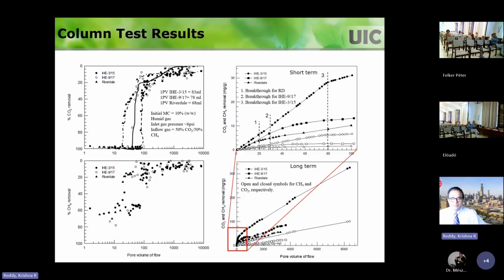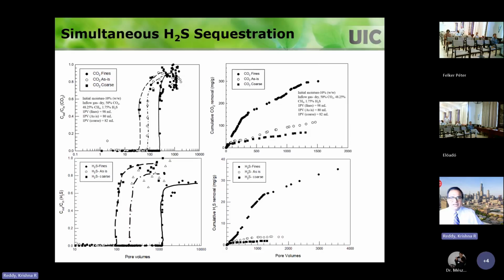You have these different minerals providing the calcium for the reactions, right? So when one easily available calcium gets exhausted, then the calcium has to come from the other mineral. It may not come as quickly as the first one. You can explore the interesting mechanisms that are happening. And then H2S, simultaneously, we had injected CO2 and H2S. You can look at it. CO2 removal, also H2S removal can also happen, which is a great thing because you can avoid the odor problems at this landfill. So a substantial amount can be taken out.